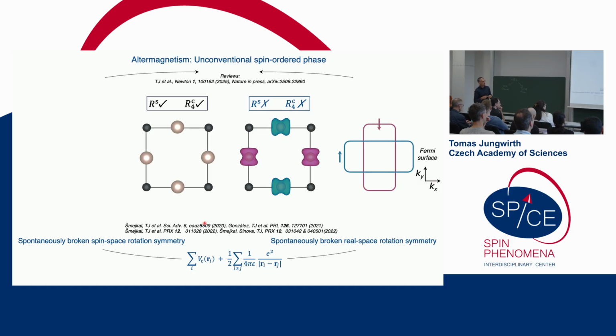So let me do this. I also think that this arguably is the simplest crystal structure on which to demonstrate this. So this Lieb lattice is a square lattice here. That means that the crystal potential has this fourfold real space rotation symmetry. And of course on top of this there is a full continuous spin space rotation symmetry, because neither of the two terms in the Hamiltonian have spin as an explicit parameter in it, so they both have the full spin rotation symmetry.